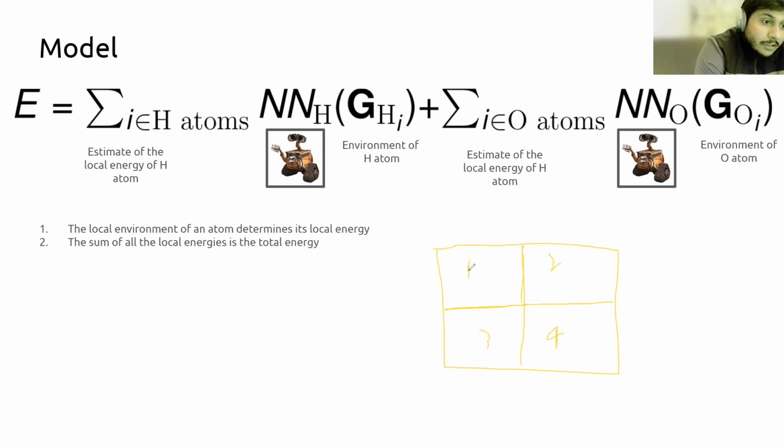Now, if you really think about it, the energy of 1 would scale with the volume, right? Because one could say that the energy of 1 should really depend on the number of atoms or entities which are in 1. While the energy between 1 and 2 would scale with the area, right? So there's a term which scales with r cube, and then there's a term which scales as r square, essentially. This is more of a back of an envelope type analysis.